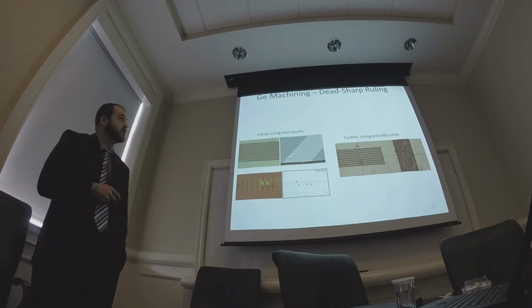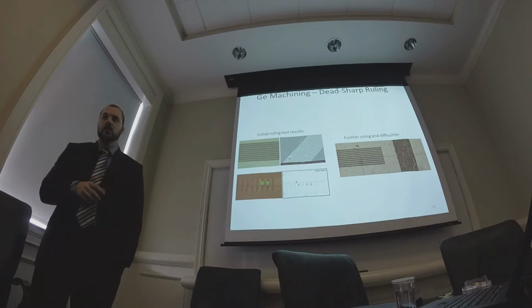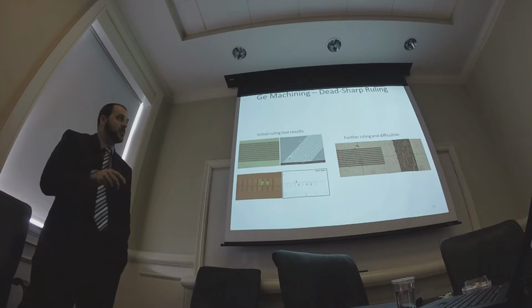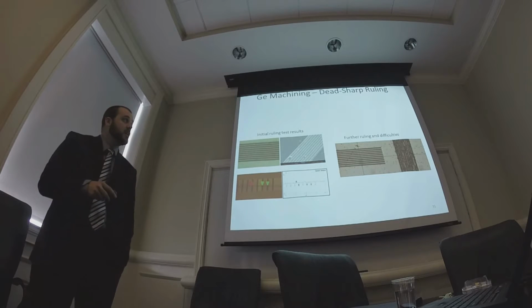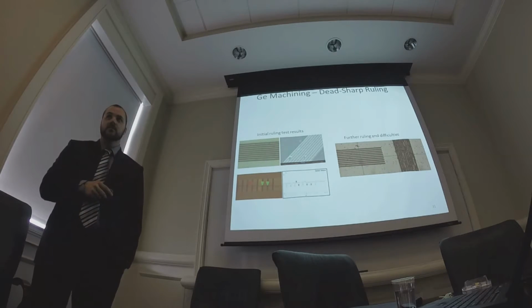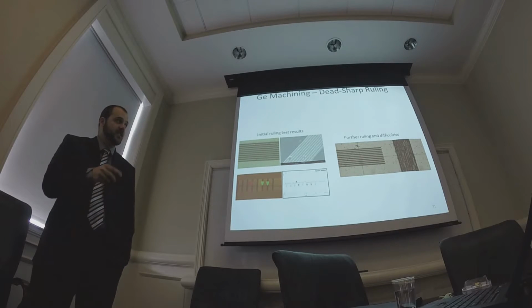Here are some dead sharp ruling examples. I've got 1 micron spacing. These were in the 200 to 300 nanometers deep. This one was programmed around one micron, but I expect it was probably closer to about 500 or 600 nanometers. The only difference between these 2 cuts is the crystal orientation, exactly like I'm showing it, 90 degrees from each other. This I had found was the best region to do cuts, and this was the worst.